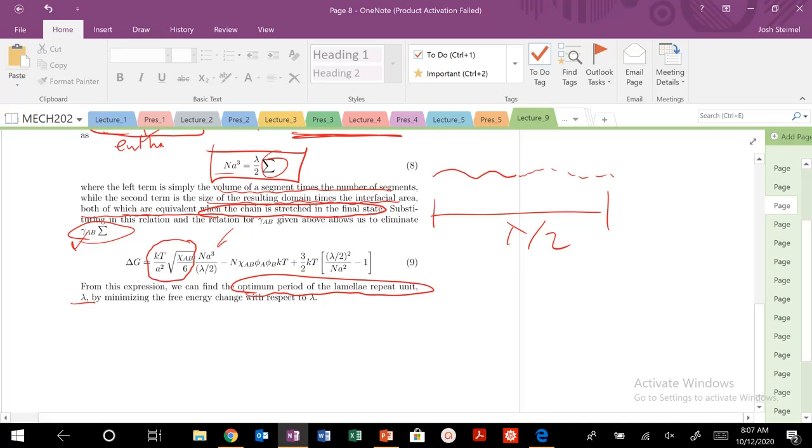The whole focus of this microphase separation discussion is that we want to be able to control microstructures. So I might have an application where, if I'm designing a circuit with graphoepitaxy, like we talked about previously, I might want to change the size or the spacing of these lamellar blocks, this lambda over 2, for my circuit. But I'm going to need to figure out, depending on all these different parameters, specifically my chi-AB for my materials, volume fractions, and number of polymer units N,